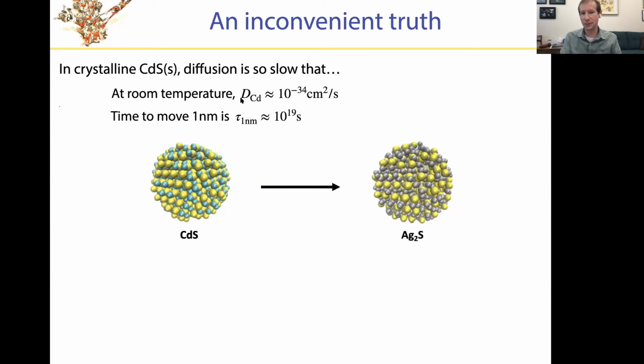If I were to use that diffusion coefficient to ask, how long would I have to wait for a cadmium ion in solid cadmium sulfide to move by diffusive motion over a length scale of just 1 nanometer? These objects are at least 1 nanometer in size. Typically, they are more like 10 nanometers. And the answer is 10 to the 19 seconds. You know how big a second is, and so you know how long that is. Again, if we divide by 10 million to put that into years, you would find that this is now on the order of 10 to the 12 years.